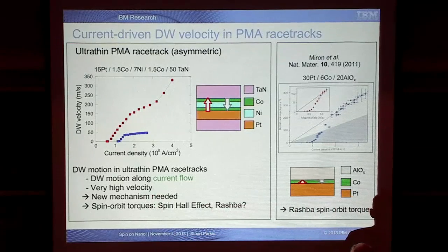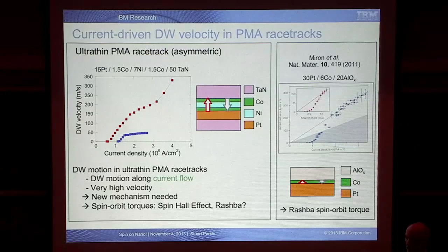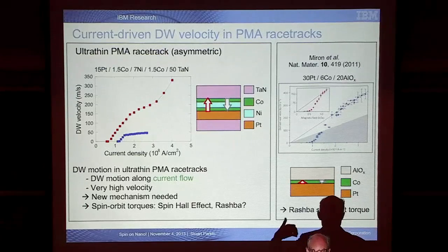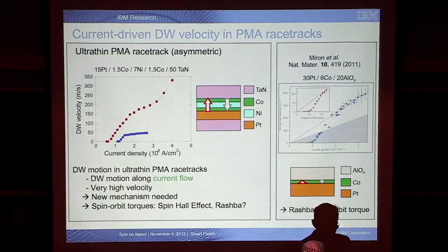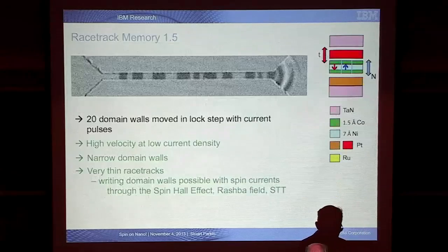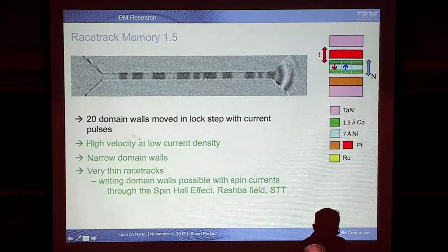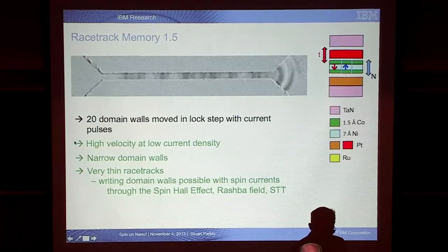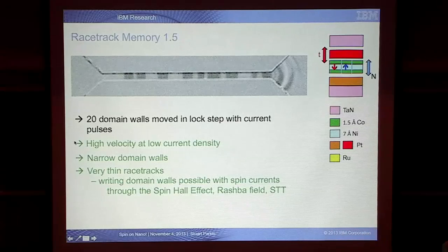And it turns out this is because of an entirely new interaction of current and magnetization, and it's because in these heavy metal layers, a charge current generates a pure spin current, which can interact with the domain walls and move them more efficiently in the opposite direction. Well, this is a very exciting development, and what we've done is we've used these materials to build a racetrack. Here you can see 20 domain walls.